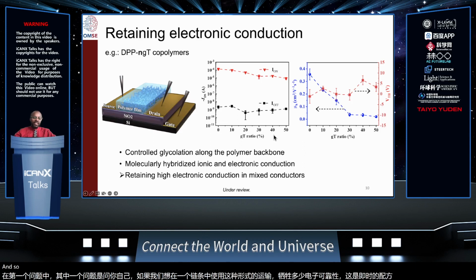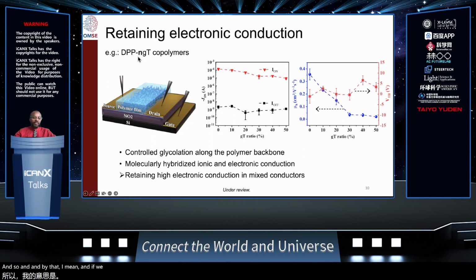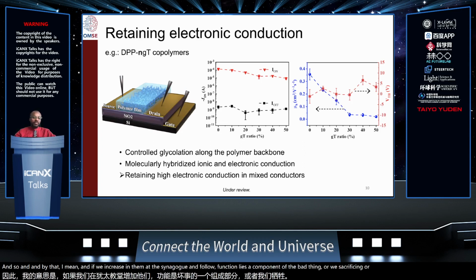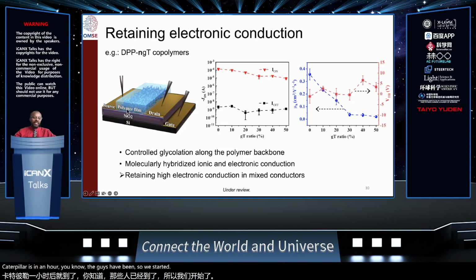By that, I mean that if we increase the percentage of the polar functionalized components of the backbone, are we sacrificing our charge carrier mobility capabilities in our devices? So we started with transistor devices. This is a conventional FET device. And then we tested how much of the charge transporting capabilities we are sacrificing by making these copolymers. As you can see here, the on-off ratio is actually not that greatly sacrificed.